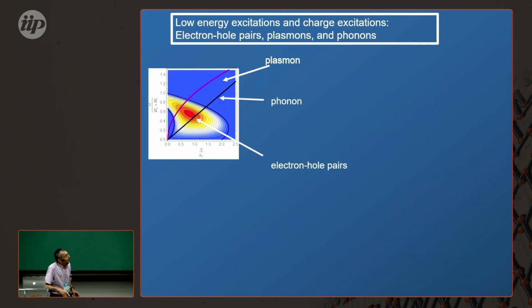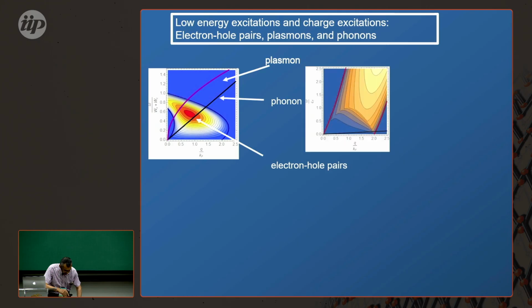Twisted bilayer graphene is very special because if you screen the interaction, you will have electron-hole pairs, plasmons, and longitudinal acoustic phonons. In twisted bilayer graphene, all these excitations occupy the same region of parameter space, which is not the case in a typical electron gas, where the phonons are at very low energy, the plasmons are at much higher energy, and the electron-hole pairs are somewhere in the middle.